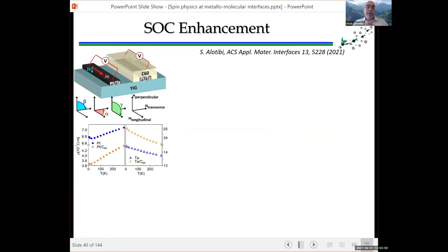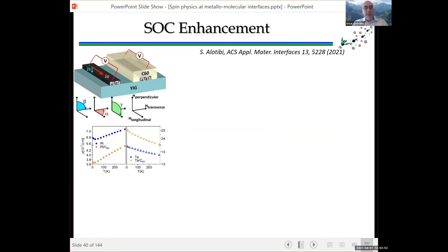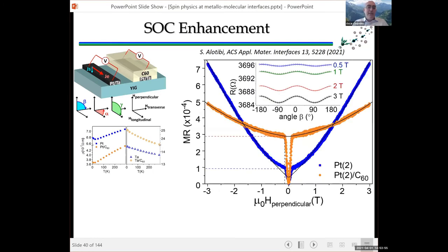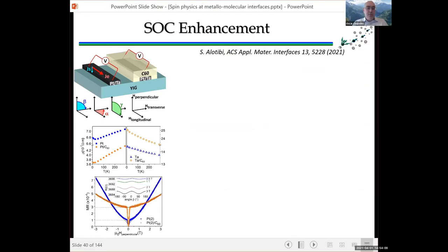And what we can see very clearly in here is that by adding the C60, so in orange, you can enhance the spin Hall magnetoresistance by up to a factor 4-5 with respect to the spin Hall magnetoresistance that you see in platinum. The same thing is true for tantalum. You also enhance the spin Hall magnetoresistance.